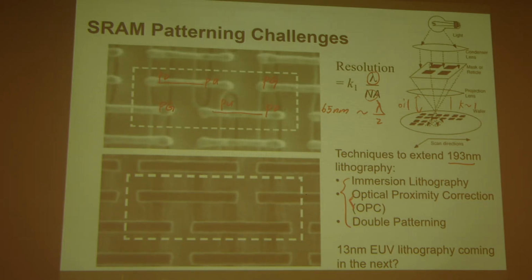So when you send the GDS file, as a circuit designer, your final product is a GDS file, and then send that file to the foundry. Foundry will make that mask for the lithography, but that's one additional step you can do there. So your mask may not be the same as your GDS file. You can do some correction there. For example, if you know at the end of the line there will be a round shape due to the diffraction, you can purely calculate this by the optics using the fundamental physics.